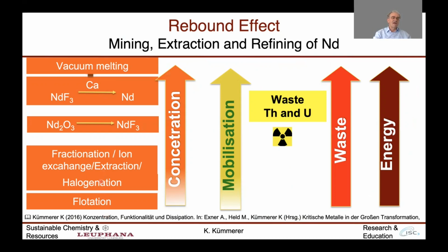You see here lots of steps. You need halogens here, and then there is physical chemical separation. And then we have here a chemical reaction. The oxide is transformed into fluoride. And then here, that's most remarkable, neodymium trifluoride is reduced by liquid calcium to neodymium.